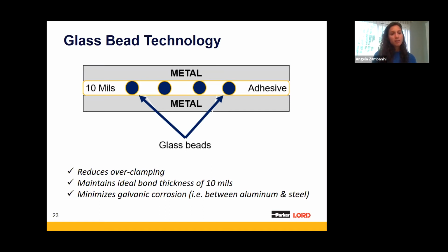Now, the second reason we put glass beads in our material is to minimize galvanic corrosion, which is the corrosion that occurs between 2 dissimilar metals, say for example, aluminum and steel. The tiny glass beads act as spacers, ensuring that the 2 materials don't touch, which is how we're able to eliminate or reduce the galvanic corrosion when multi-material bonding.